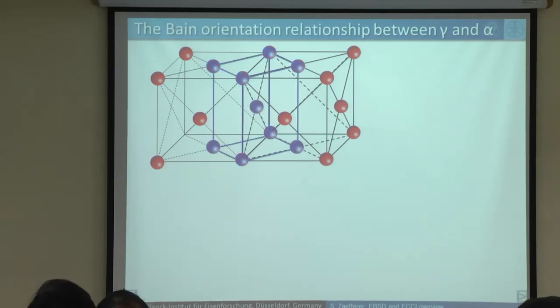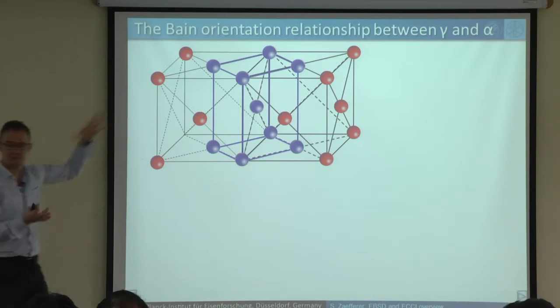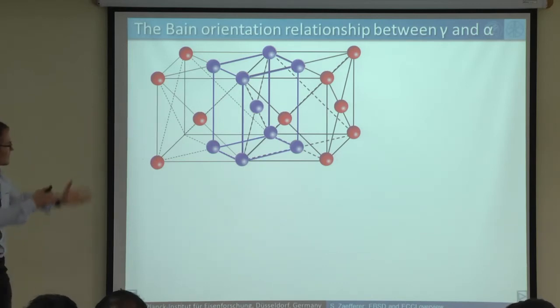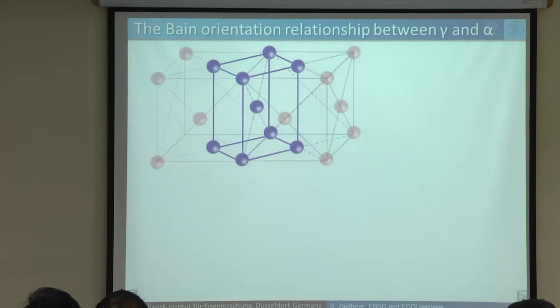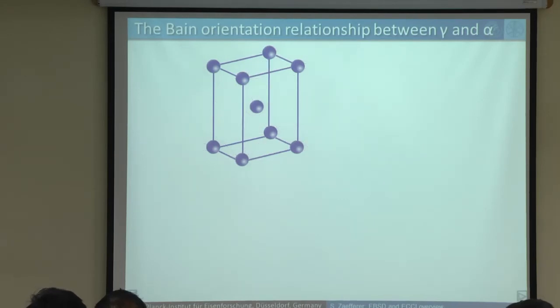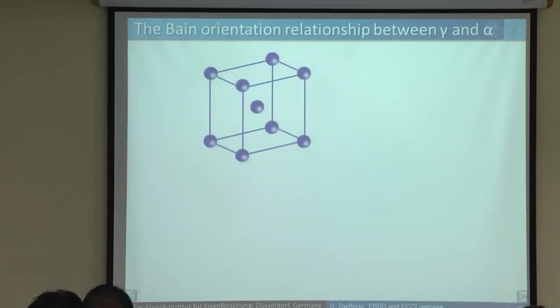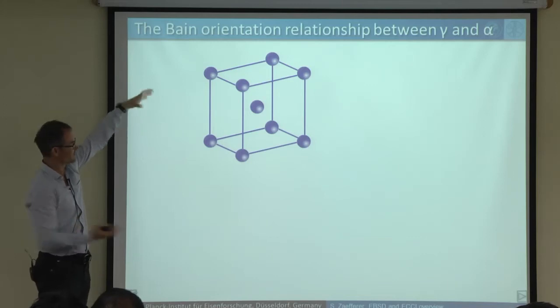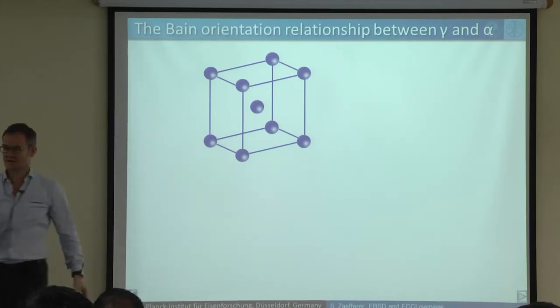It's actually here, marked in blue. Yeah? It's not yet BCC because it's still tetragonally extended. But in principle, inside of austenite, there is already the ferrite atomic arrangement. And now in order to actually get a ferrite, you don't need any diffusion. You just need to make this transformation and then compress the ferrite a little bit, or the BCC, the tetragonal lattice a little bit, and you come to the cubic lattice.